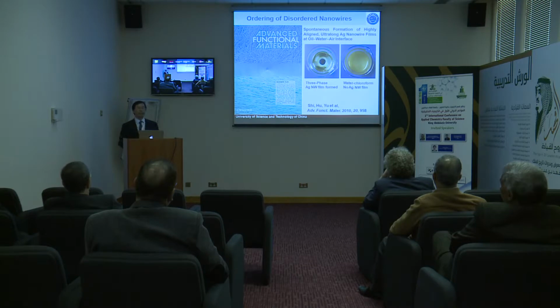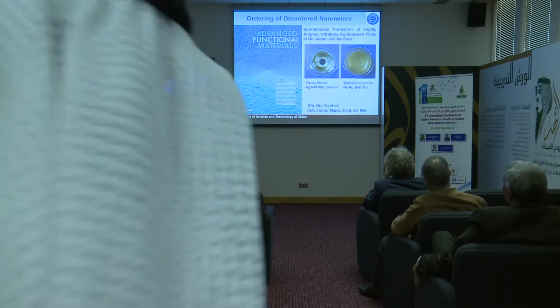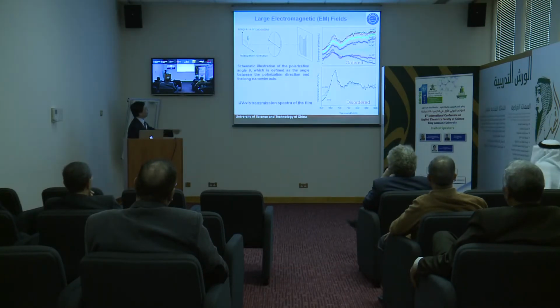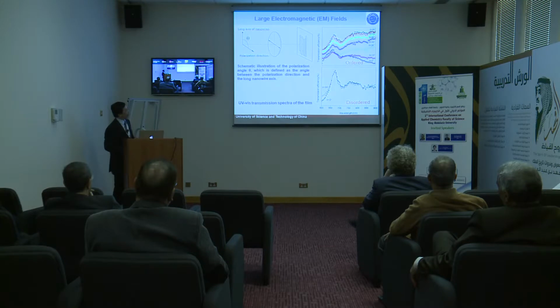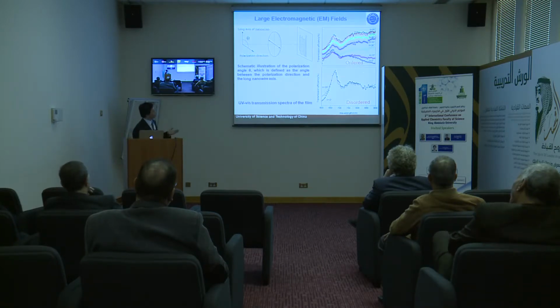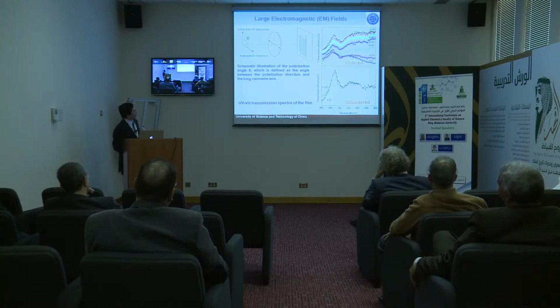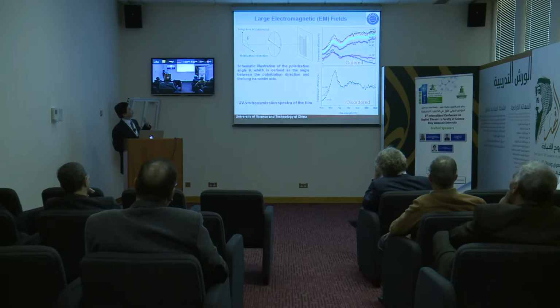Compared to the individual nanowires, the nanowire assembled structure is more reliable for nano device fabrication in the future. So to give one example, this is the silver nanowires. We make this silver nanowire become ordered. Then later on, we find that compared with the disordered nanowires, the silver nanowire assembled structure thin film, for which we use a very simple dip coating strategy. You will see these randomly aligned nanowires. You will see the transmission efficiency. You can't find this polarized angle dependent transmission efficiency.